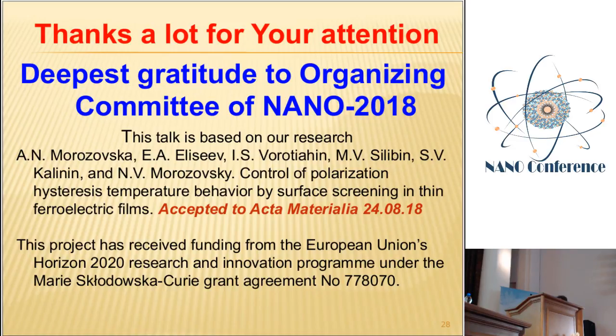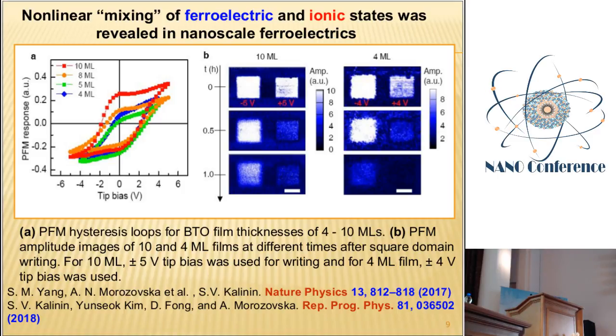Yes, in experiments we have barium titanate, lead zirconate titanate, lithium niobate films, but the results that are already published, I show them on this slide. It is a barium titanate film. It was deposited on a strontium titanate substrate, so the misfit strain between the film and substrate was small enough, and the top surface of the film was electrically free, but exposed to oxygen pressure. The distance between the scanning probe tip and the top surface of the film varied in accordance with the goal of this experiment. This is barium titanate from 10 monolayers to 4 monolayers film. We also have almost the same results for PZT film, but I do not show them because they are unpublished.